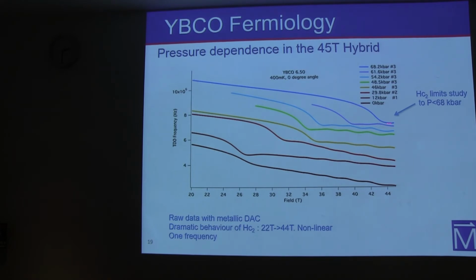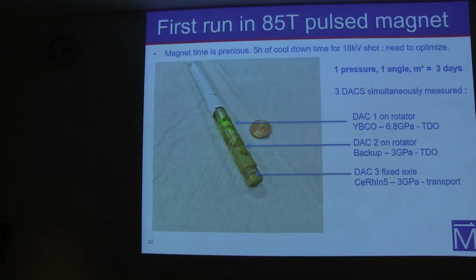And then by basically 70 kilobar, we literally run out of field in the 45 Tesla magnet. So 45 Tesla is no longer enough to see quantum oscillations and continue our study. So we have to go back to pulse magnet to look at the next pressure range, which is really different. And so this is what we did recently. That was our first run in Dresden in the 85 Tesla magnet. Usually we run the 70 Tesla magnet, but we managed to get access to the duplex magnet, 85 Tesla.